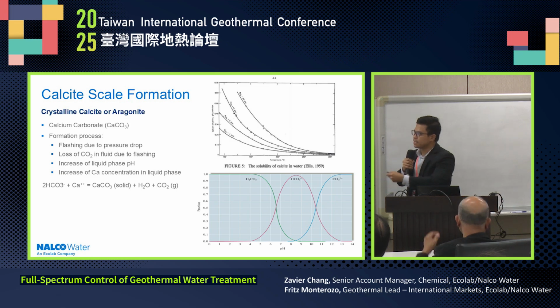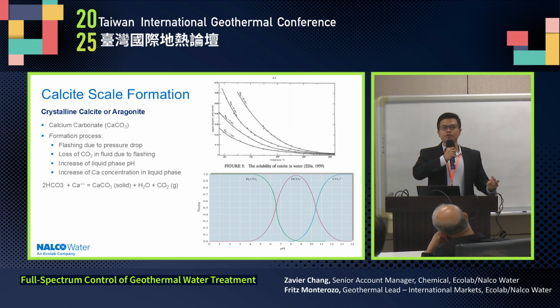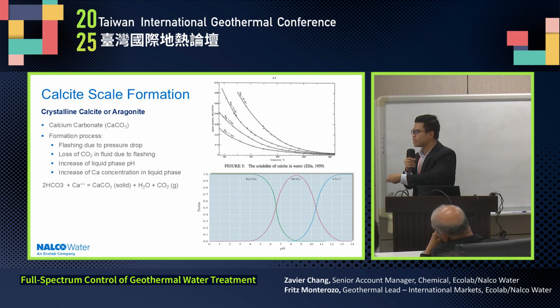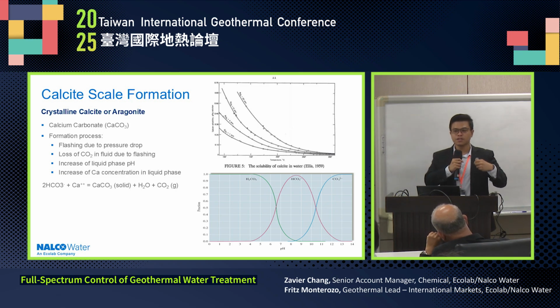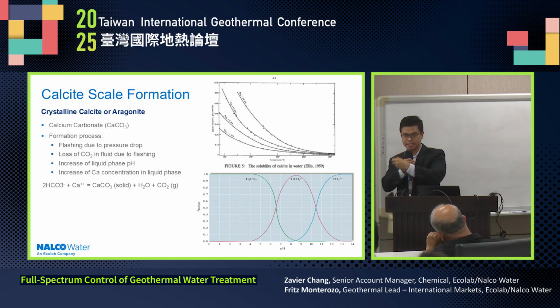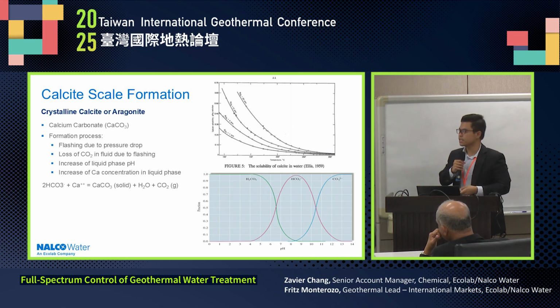So what happens is, before you bring your fluid to the surface, it is still single phase. As your fluid rises up, your CO2 is being released from the solution, and what happens is your pH increases. So calcite is more soluble in acidic conditions. But once you release the CO2, it becomes more basic. It becomes more alkaline. So it pushes the reaction forward, forming more calcite deposits.